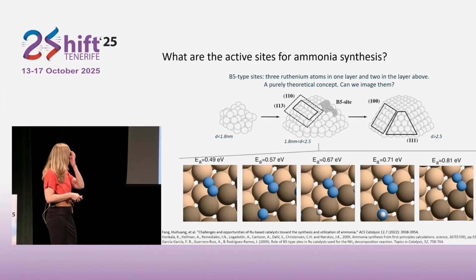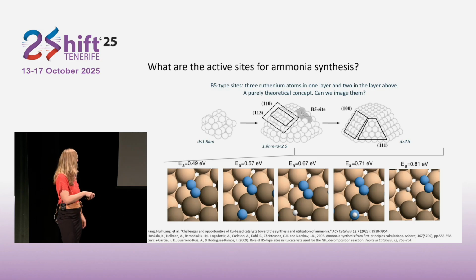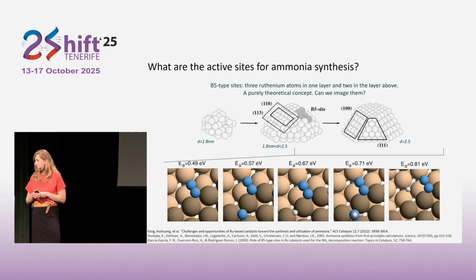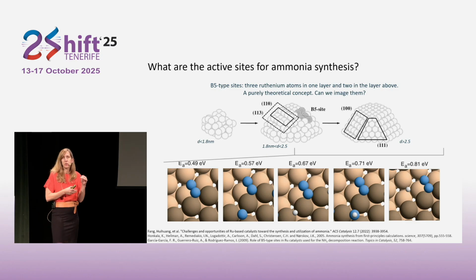Okay, so in the final few minutes before I switch to some bio applications, I wanted to show you what might be happening on the surface of these catalytically active nanoparticles. And at least what's hypothesized is that when you have a nanoparticle in a certain size regime, you have these step terraces that correspond to B5 sites. So a B5 site would be 3 ruthenium atoms in one layer and 2 in the layer above.